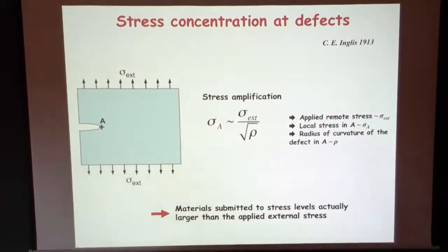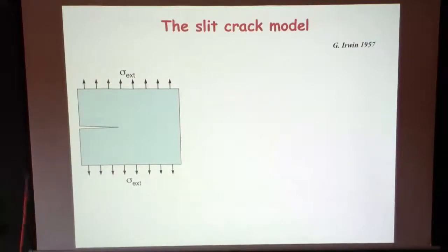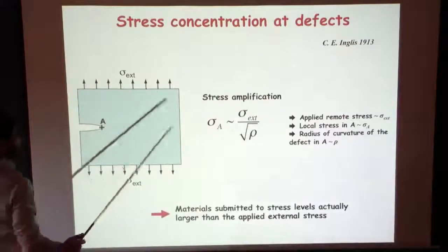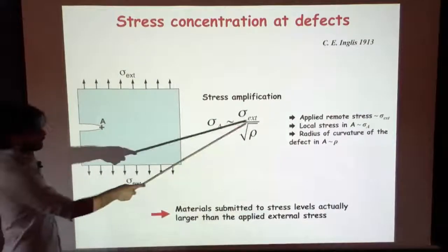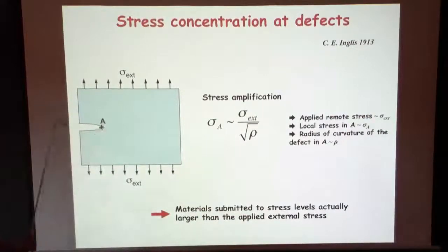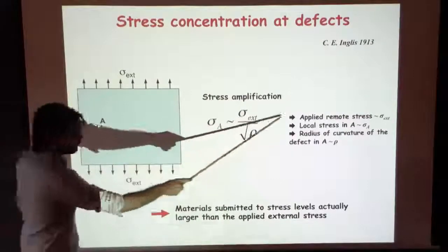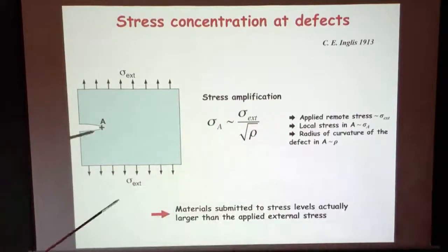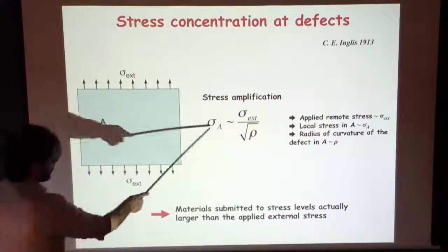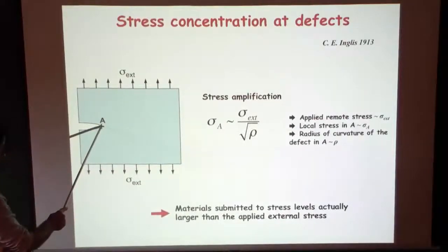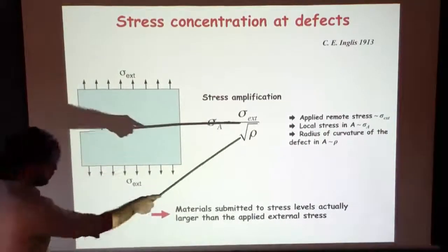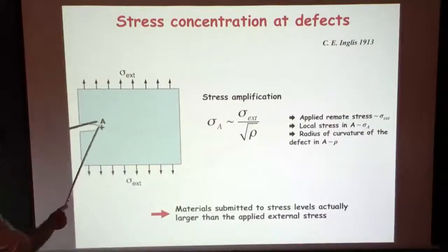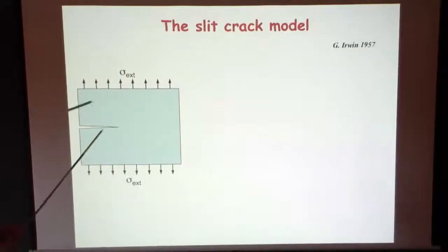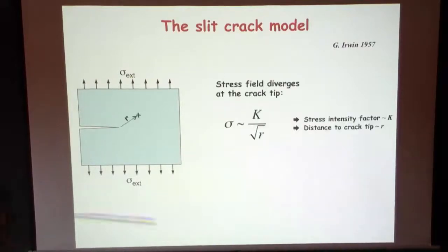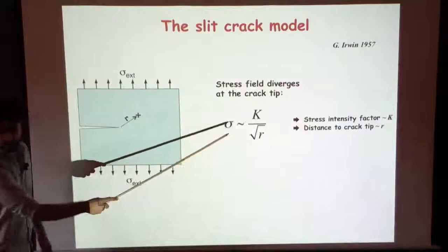Then to come to the point of J. The prefactor? Which prefactor? Sigma ext. There is a length scale missing that is actually the length of this cavity in this direction, square root of. The next one is very different because you cannot go from this one to the next. Since I consider only the stress field in A, rho tends to 0, I have an infinite stress in A. That is consistent with the result here. At the tip, I have r equals 0. I have an infinite stress. That doesn't tell me so much.